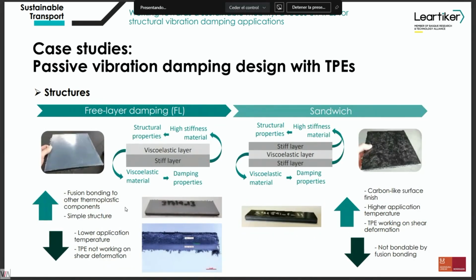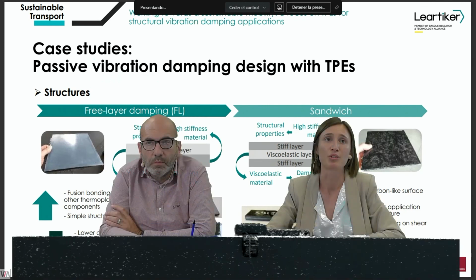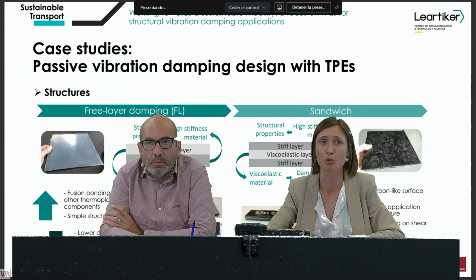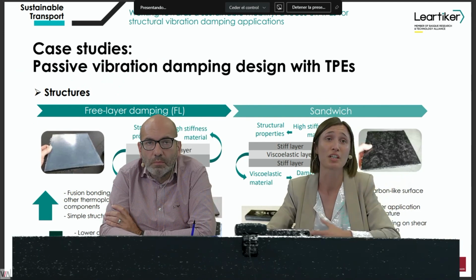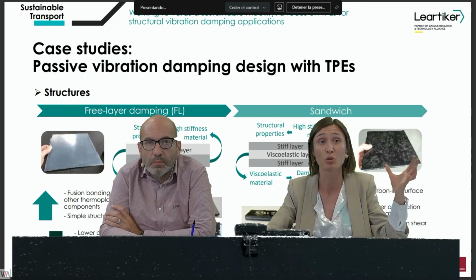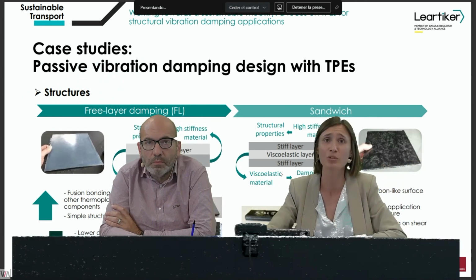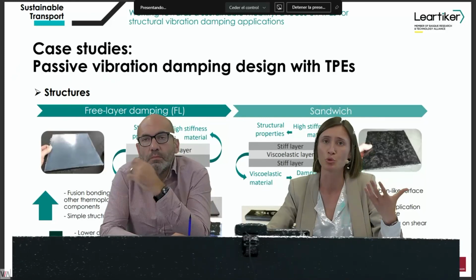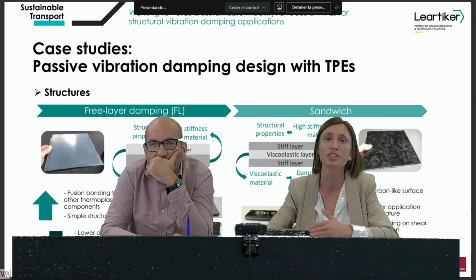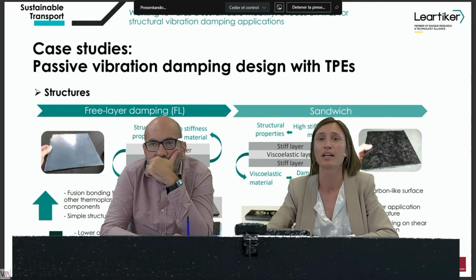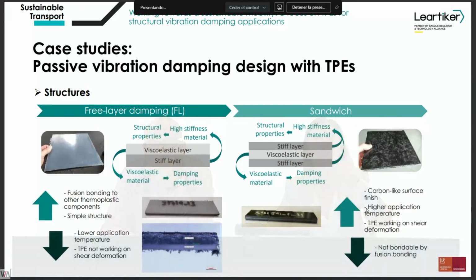So these are some pictures of the structures that we developed. On the one hand, we made free layer damping structures, which are very simple and widely used in the automotive sector, mainly due to their simplicity. And then we also made sandwich structures, mainly because in sandwiches we saw a higher application temperature range. But as I said, in this case we are targeting room temperature, and high temperature is not key for this application, so we will focus on the free layer damping.